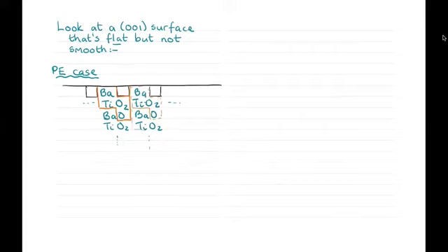And down here, I'll capture this oxygen that I haven't drawn, put it in, and build up the entire semi-infinite plane of barium titanate. So we can follow our recipe and work out the bulk polarization for the paraelectric structure as the dipole per unit volume of this unit cell. Let's take Z equal to 0 to be at the oxygen, which of course has a charge of 2 minus.